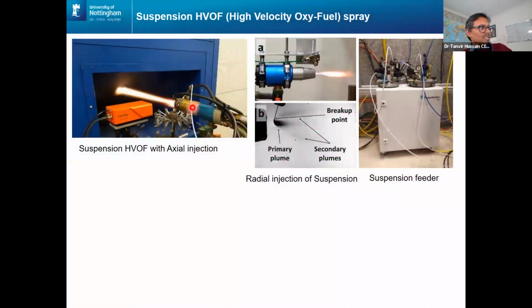What we have used to produce this is our high velocity oxyfuel, or HVOF, torch. It has a bespoke nozzle in front of it as a shroud. And this Tecnar system looks into the flame and can pick up particle velocity and temperature. We can inject suspension axially as well as radially. For oxygen sensitive systems, radial injection is much preferable. We have a suspension feeder, which was originally developed at Fraunhofer, but then we modified it to have a closed loop system with pressure control. So we can control the amount of liquid being injected. And here you can see with some imaging technique how we inject the liquid, what happens to it, and how it breaks up.